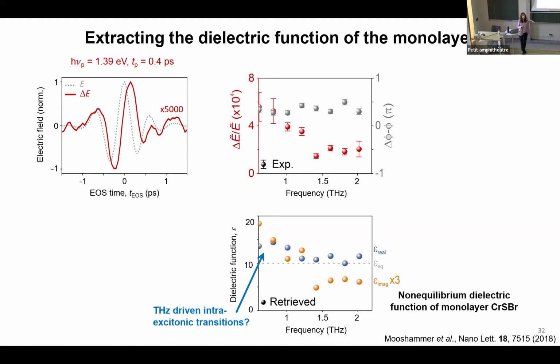How can we understand that we have this terahertz-driven intra-excitonic transition from higher lying excitonic states? Because actually, when we have the 1s state, 2p state, 2s, etc., the higher we go in excitonic orbitals, just like the hydrogen atom, the more the orbitals get close to each other, right? So when we have excitons in these higher lying excitonic states, a terahertz pulse is able to generate transitions between these closely spaced excitonic orbitals in energy space.